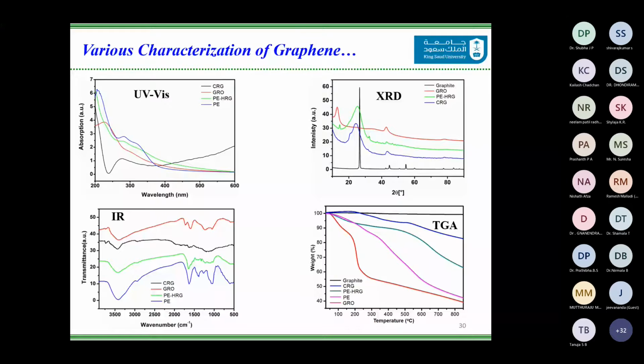Moreover, we also did the TGA, thermogravimetric analysis, of the highly reduced graphene that we obtained. And we found that the highly reduced graphene obtained from plant extract is slightly thermally less stable than the chemically reduced graphene. The reason is that there is a loss of weight observed. However, this loss of weight can be attributed to the phytomolecules present on the surface of this graphene, which decompose at elevated temperatures.